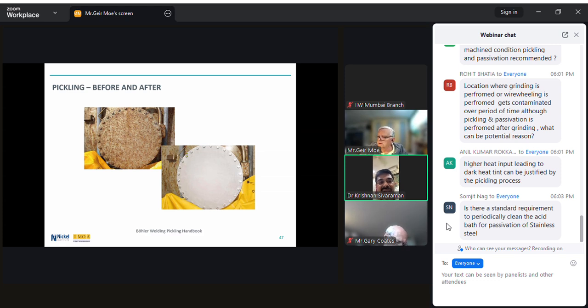Right. And there is one question on stainless steel casting. When it is machined, is pickling and passivation recommended? It's not always necessary, because if you're machining with, say, tungsten carbide, you're generally not going to be contaminating the surface. Whether it's a stainless steel casting or even a forging, like forged flanges, that are machined, you wouldn't necessarily need to passivate it, but you might, just for cosmetic reasons.